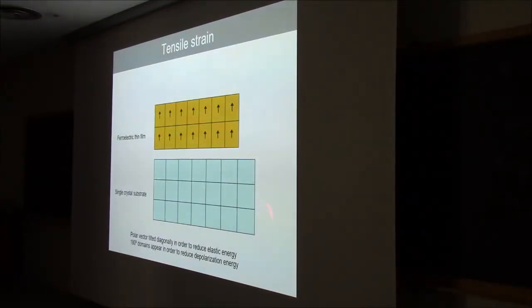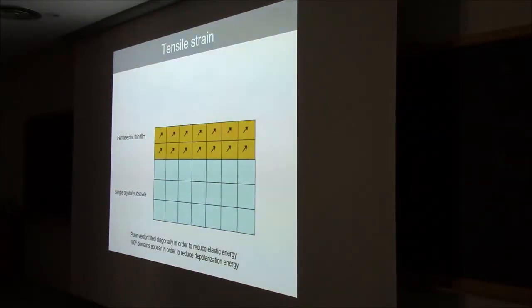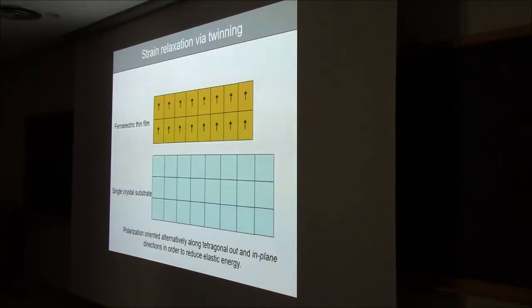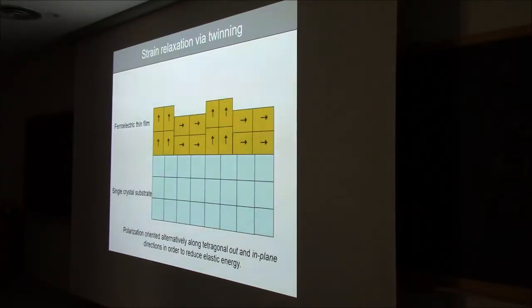So this is the idea. You take your substrate. I have my tetragonal ferroelectric that I want to grow on this, but this has a bigger lattice parameter than this. So what happens is that the polarization tilts, and that way it adopts a lattice parameter that is closer to that of the substrate.